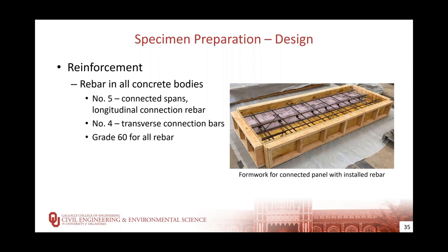These were cast upside down so we could use foam inserts to shape the connection outline. The photo on the right shows the formwork, form insert, and all the rebar tied in and ready for the concrete to be poured. About 6 inches of rebar of what would be the top layer of rebar was extended into the foam to be spliced to the adjacent span's rebar later on.